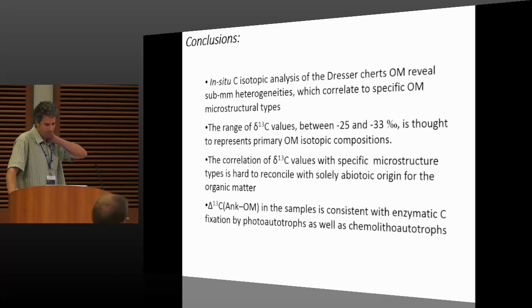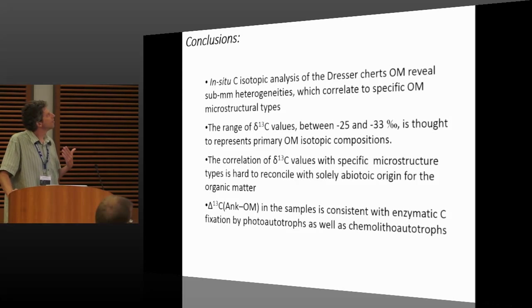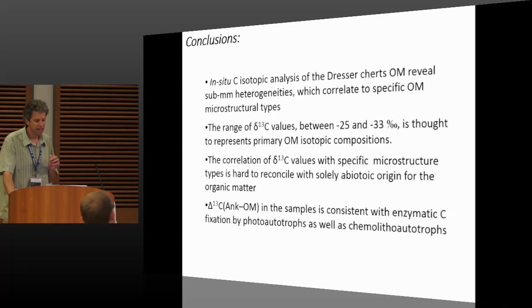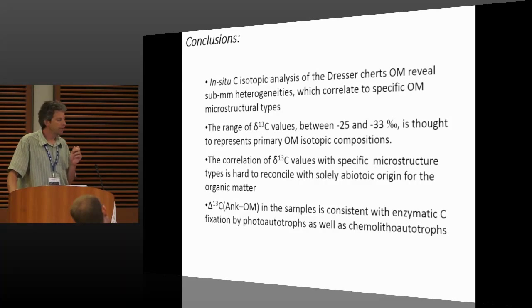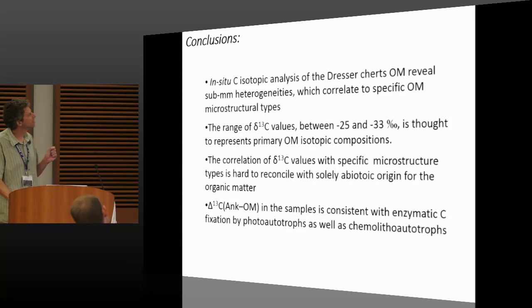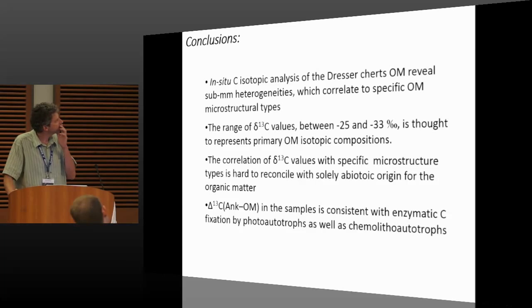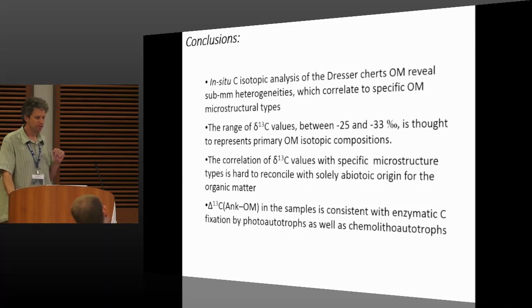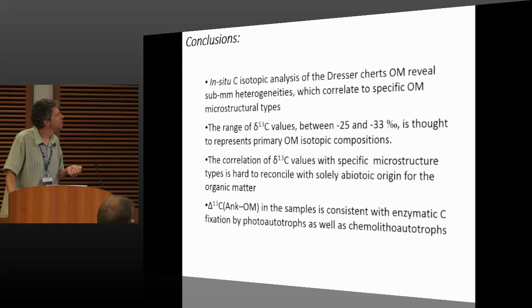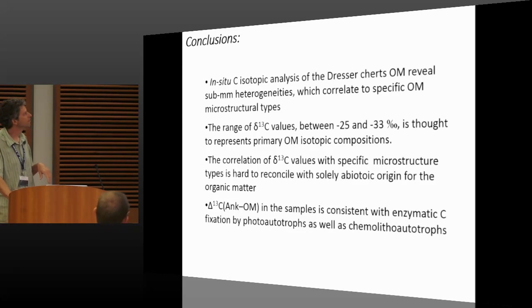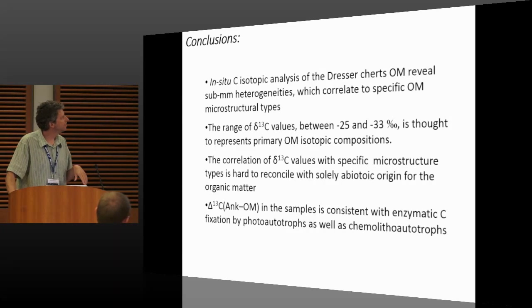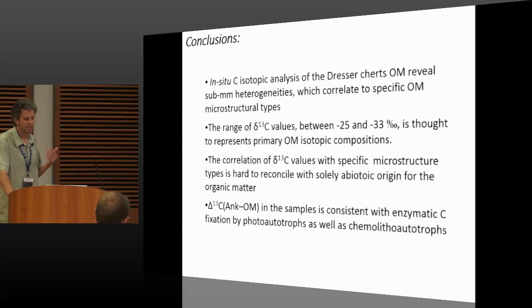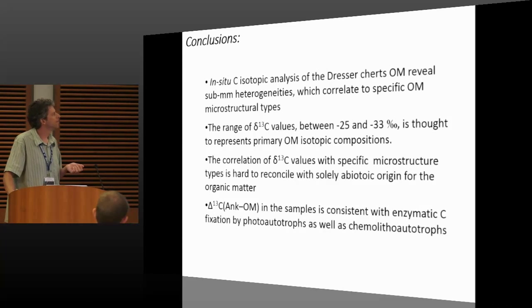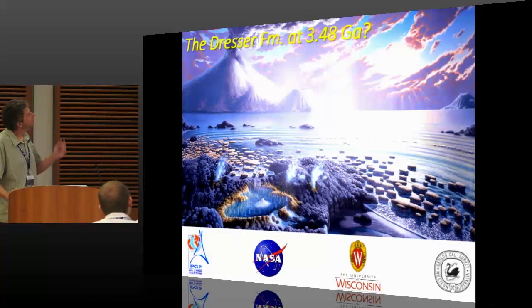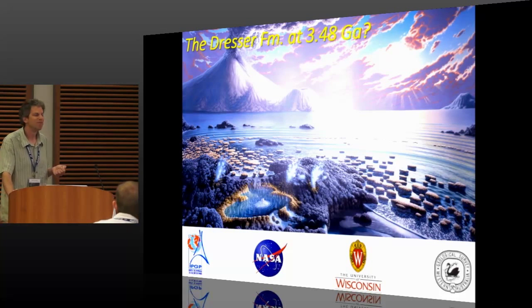So just a quick conclusion. We have shown that in situ carbon isotopic analysis in the Dresser reveals submicron heterogeneities which correlate to specific microstructural types. And the range of values is thought to represent the original primary organic matter isotopic heterogeneity. And the correlation between isotopic composition and specific microstructural type is hard to reconcile with solely abiotic origin for the organic matter. And the fractionation between inorganic and organic carbon in the sample is consistent with enzymatic carbon fixation both by photoautotrophs and chemolithoautotrophs. And I will finish with this artist impression of early life.